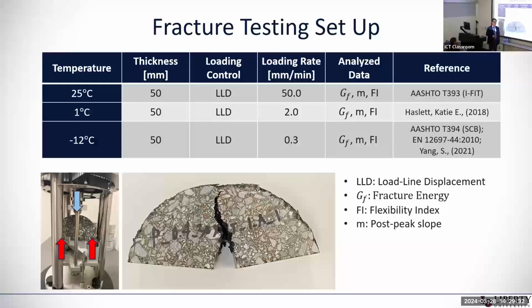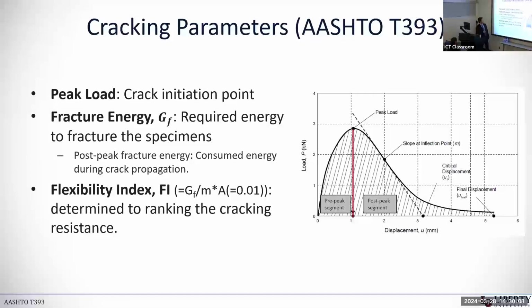And then for the loading rate, we start from the very slow loading rate and the high loading rate, but this specification uses the CMOD control that actually gives the crack propagation. But if you apply the load line displacement control test at the low temperature, it's really hard to control gradual propagation of the cracks. So we had some trial and error, and then we decided to use 0.3 millimeter per minute, load line displacement controlled. We look at the peak load, fracture energy, and the flexibility index as well to figure out what is the impact of these fibers on the asphalt cracking performance.